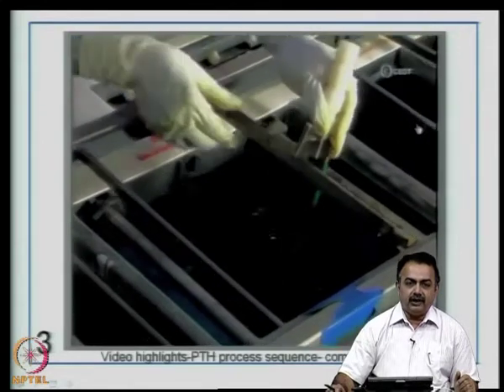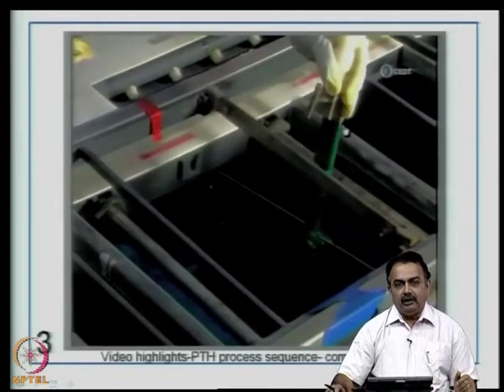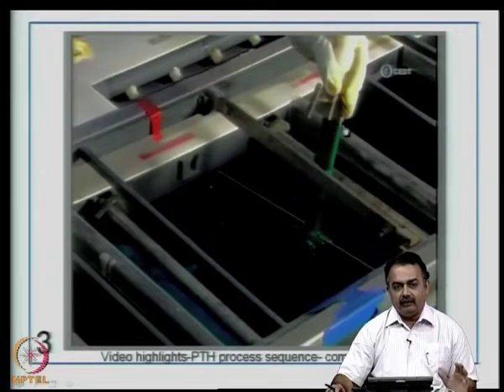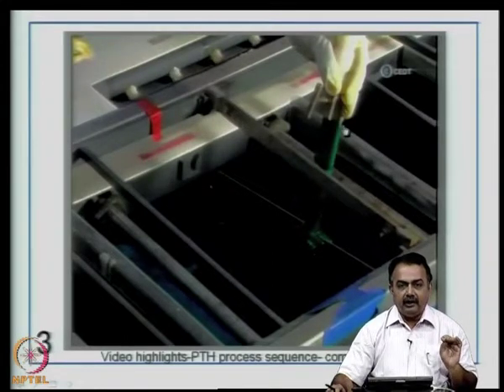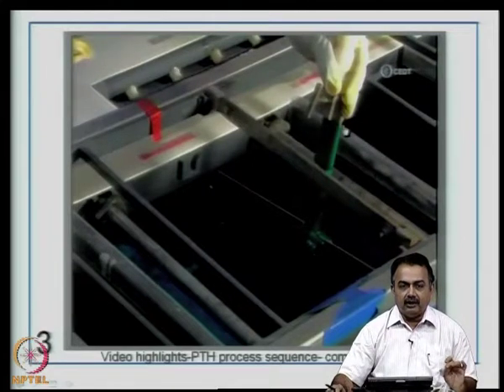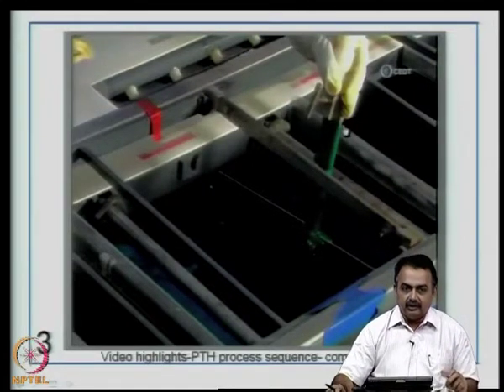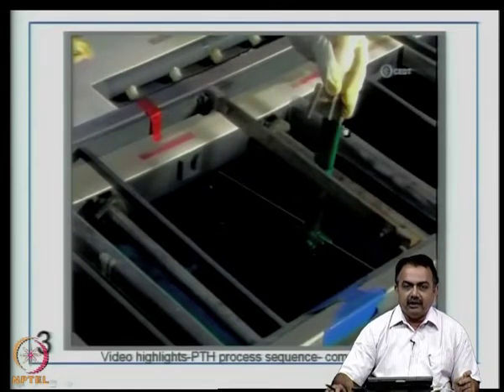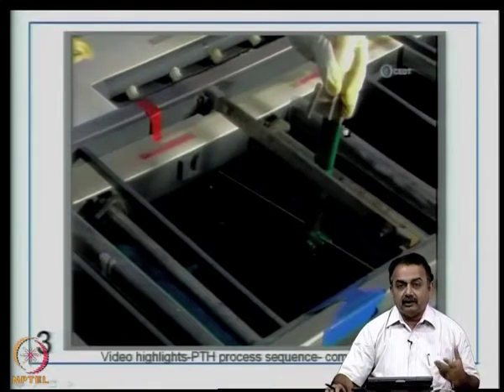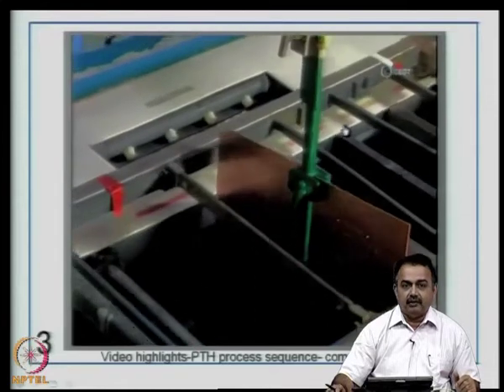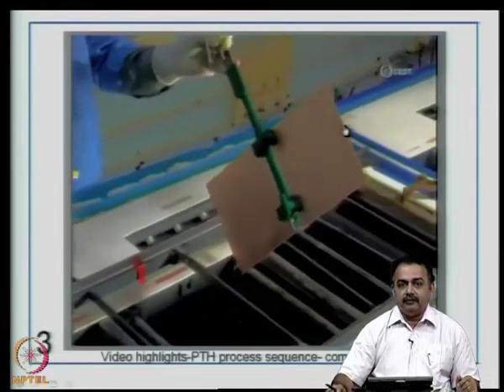Now, after sufficient time, here in copper plating, you have to calculate the area to be plated. There should be constant agitation, there should be good air circulation, and the distance between the anode and the cathode has to be measured, and accordingly you have to set the current density. Typical guideline is 20 amperes per square feet, and it depends on what thickness you want to plate. Your final thickness, if it is around 32 microns or 35 microns, accordingly.